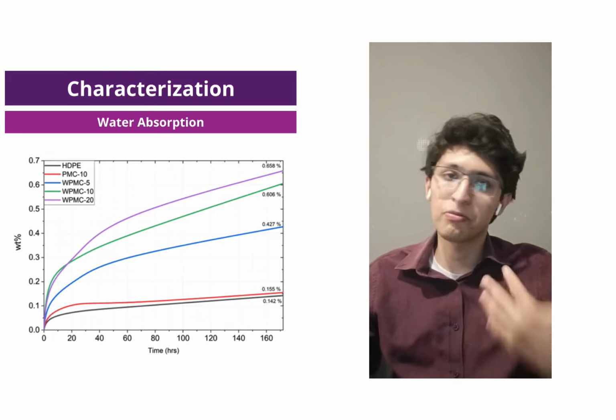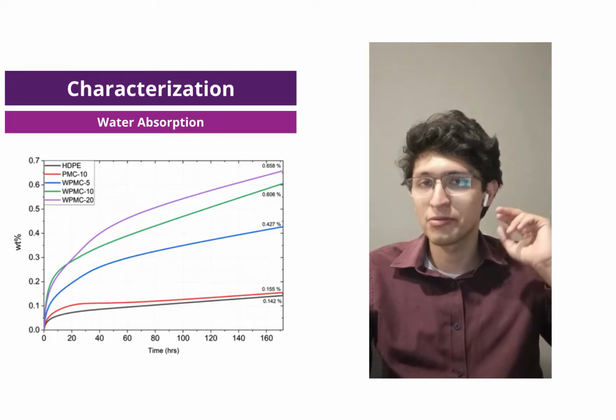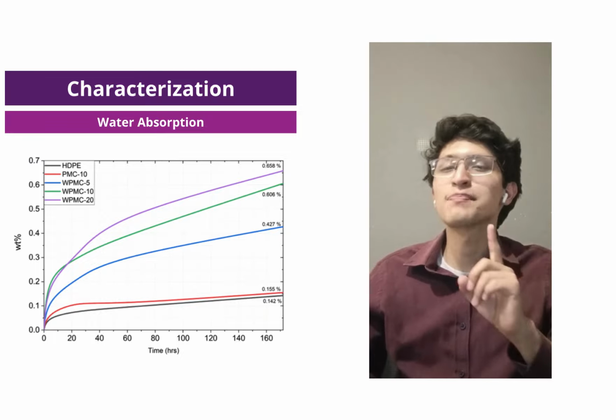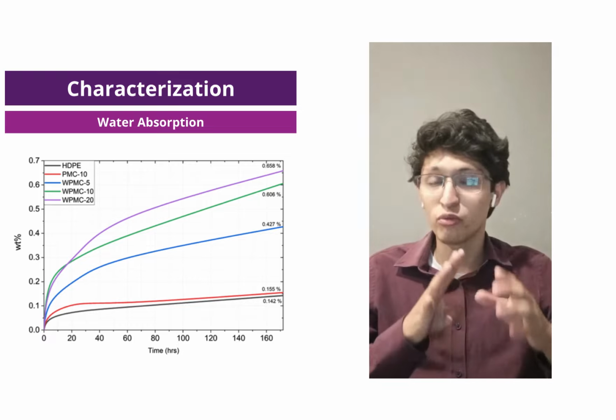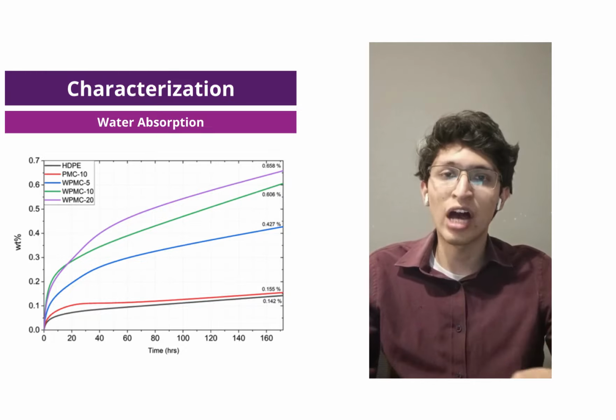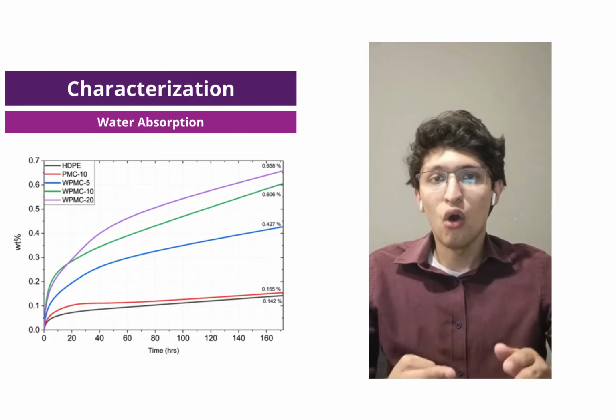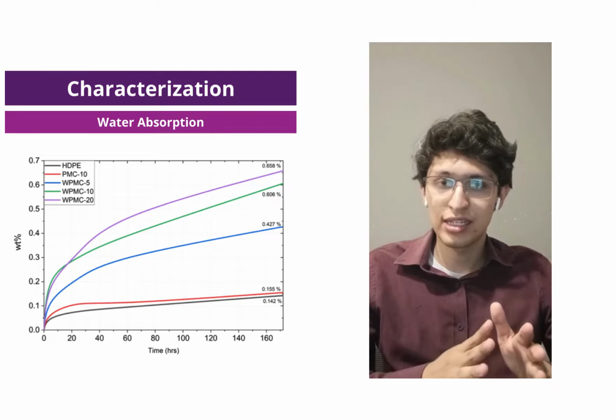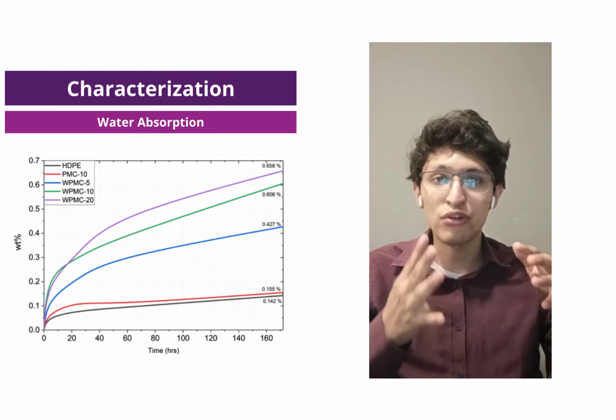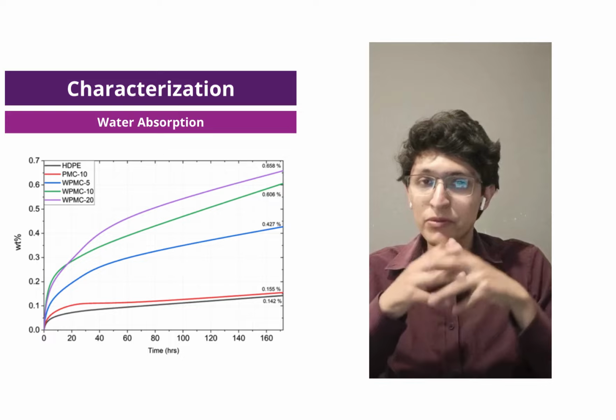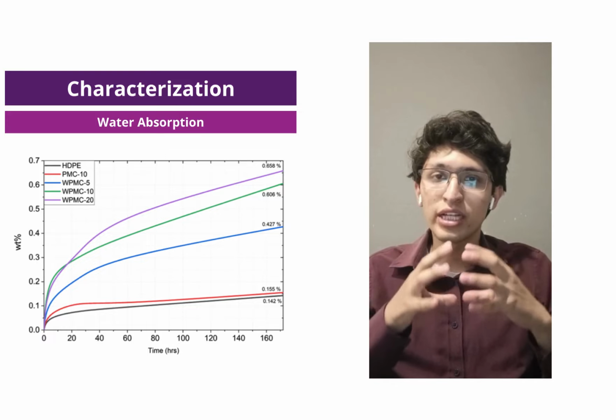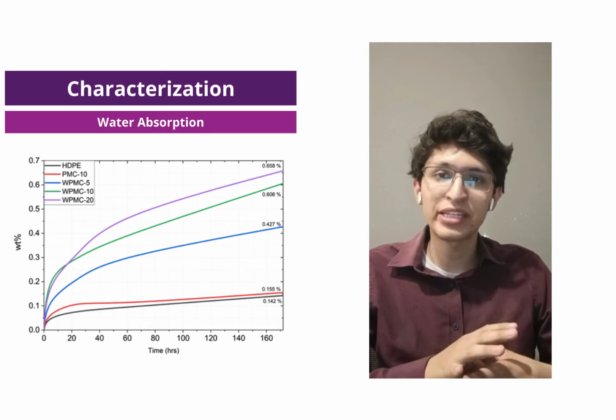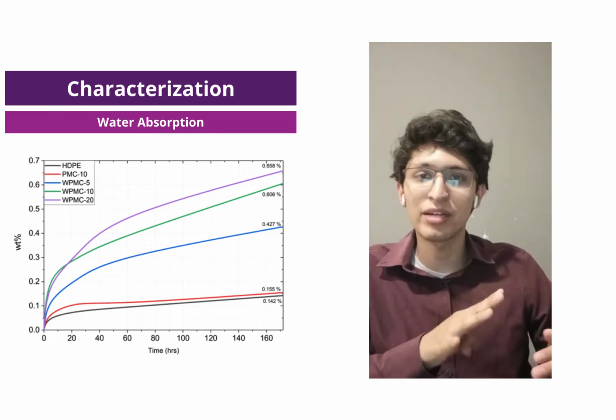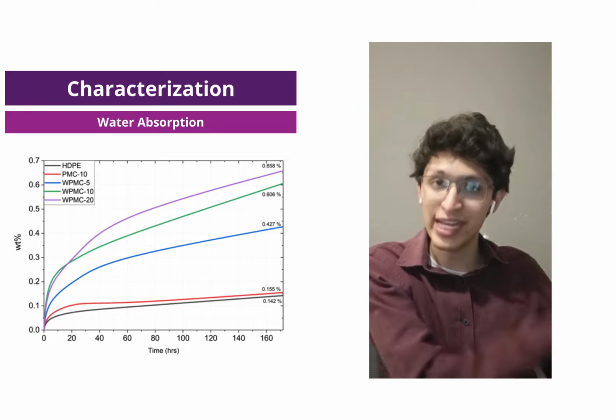Now, about the water absorption rate, we can see a very expected result. With the presence of wood fibers, we can see an increase on water absorption rate. But why does this happen is very interesting. Yes, the wood fibers are absorbing water, but they are also forming a porous phase on the polyethylene matrix. This porous phase allows water to penetrate and reach previously encapsulated multilayer plastic that it did not previously interact with, increasing the rate with the multilayer plastic percentage.